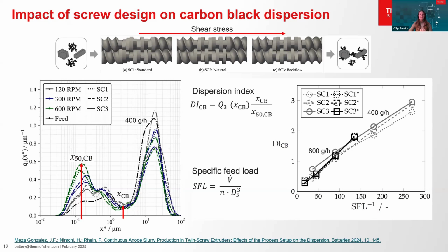De-agglomeration of carbon black is a significant challenge in the mixing of the electrode slurries. Through simulations of a digital twin and experience with 3 different kneading section designs, shown here on the top, 2 different throughput rates, and 4 screw speeds, a correlation was found between process parameters and the particle distribution of the anode paste. In the left graph, you see the particle size distribution in anode slurries mixed with the different screw designs and different screw speed. The dispersion index can be calculated from the median of the carbon black fraction from the size distribution. The higher it is, the smaller are the carbon black agglomerates.